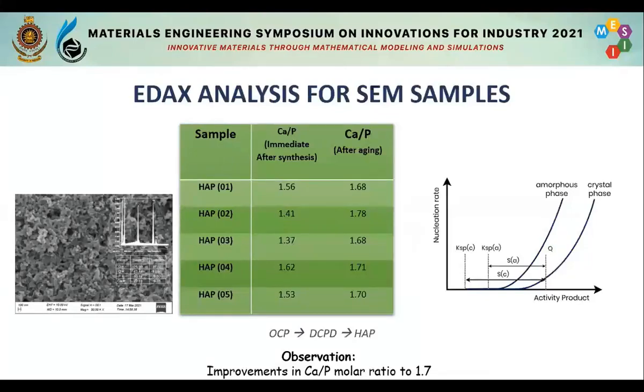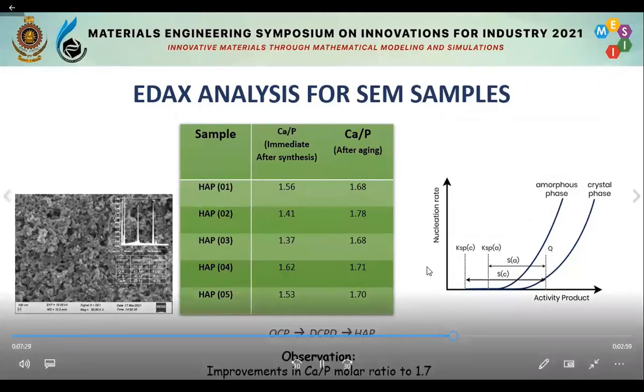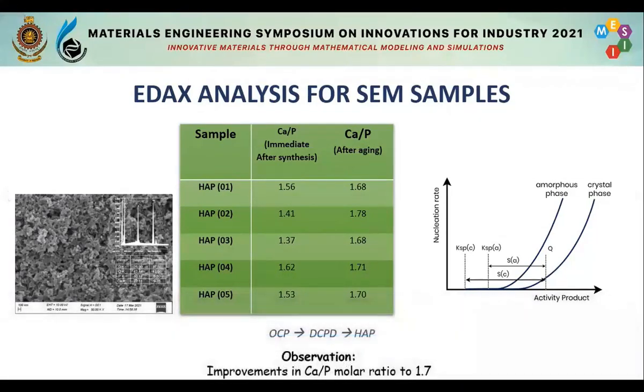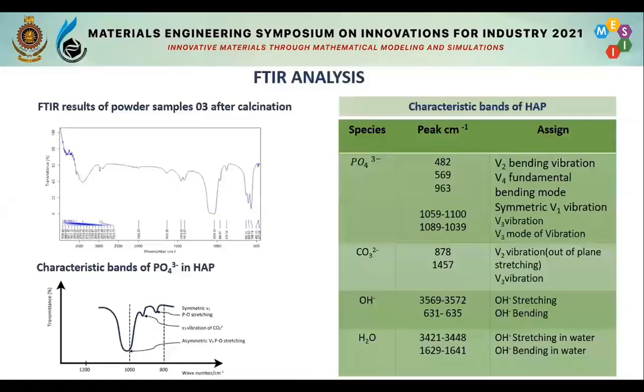In the EDX analysis part, the calcium to phosphorus molar ratio initially was near 1.56, but after aging, it increased to 1.7, which is the characteristic ratio for hydroxyapatite. We can assume that hydroxyapatite formation happens not in a single step, but in multiple steps.